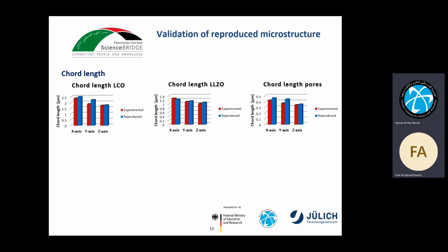For the chord length of pores, we can see an almost matching pattern with the chord length of LCO, which means that the shape, the orientation actually, and the distribution of the LCO particles are affecting the chord length of pores, the shape and the orientation too.